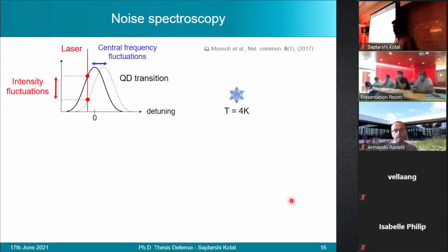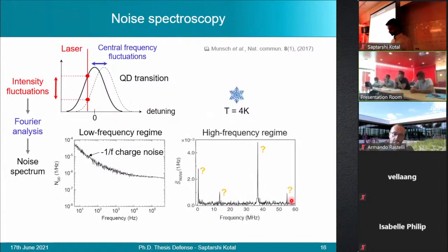Next, to understand the cause of this broadening, a spectroscopy of noise was carried out on the quantum dot by now setting the energy of the laser slightly detuned from the quantum dot resonance. In so doing, it made it possible to probe all the sources of noise that are responsible for making the central frequency of the quantum dot fluctuate. By doing a Fourier analysis on the resulting intensity fluctuation of such a signal, the following spectra were observed.